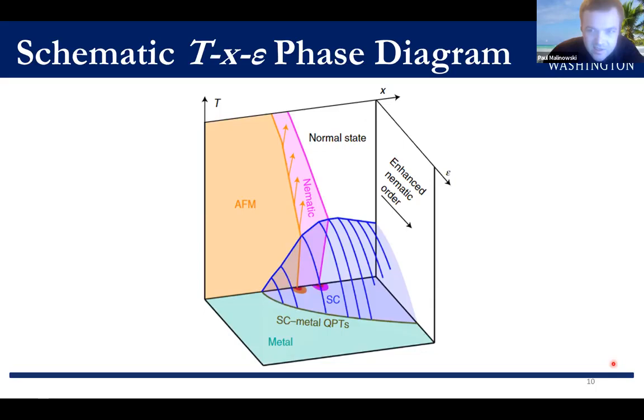Now, these findings are interesting for a few different reasons. So one, in the case where superconductivity can be completely destroyed, this provides a platform for studying a superconductor to metal quantum phase transition in a bulk 3D system with strain as a clean in situ tuning parameter. And two, it's a direct demonstration of the importance of the fluctuations of the competing nematic and magnetic phases, because in the same sample, we can use strain to strengthen or weaken those fluctuations and see how the superconducting state responds.